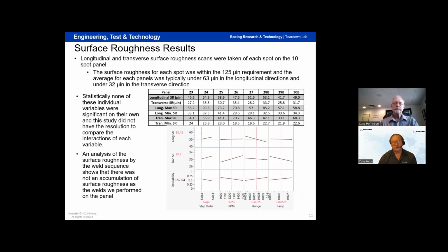So we were able to, starting with the surface results, surface roughness, what we did is we measured the bottom sheet, so the bottom of the bottom sheet, which would be equivalent to the side that sees the air flowing past it. And we measured the surface roughness both in the length of the weld and across. So we do essentially a plus sign on the back of the weld. And all of them were within 125 microinches, which is a typical requirement.